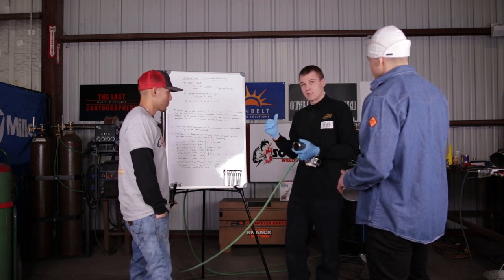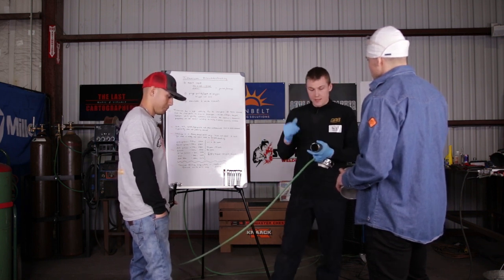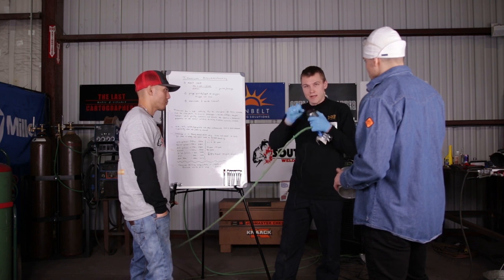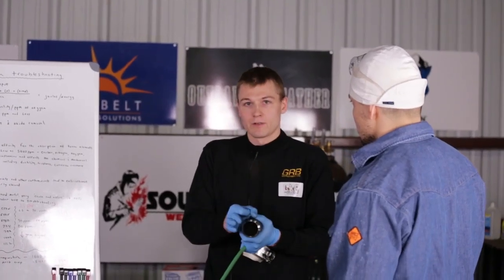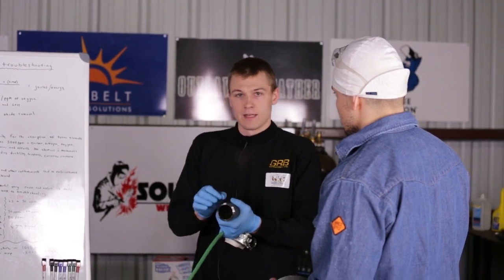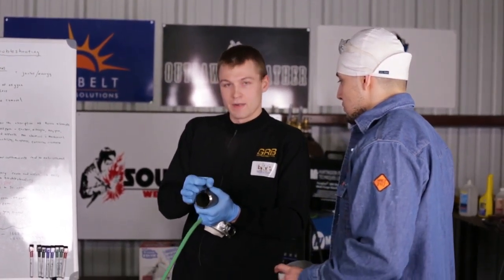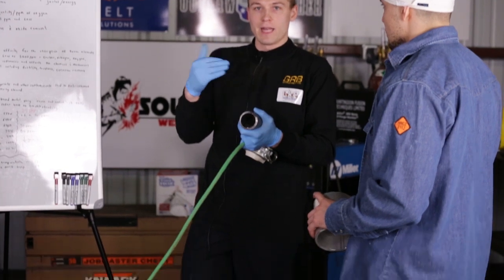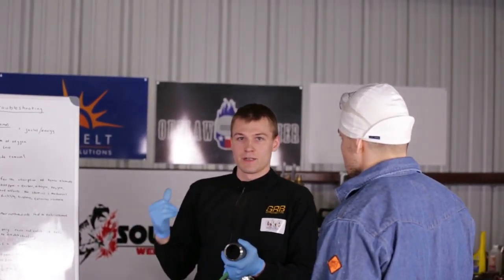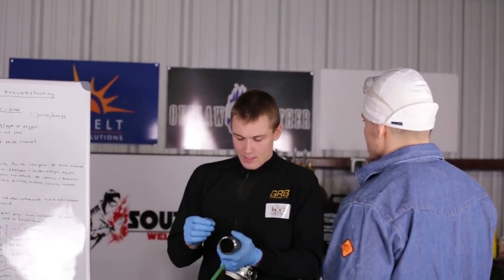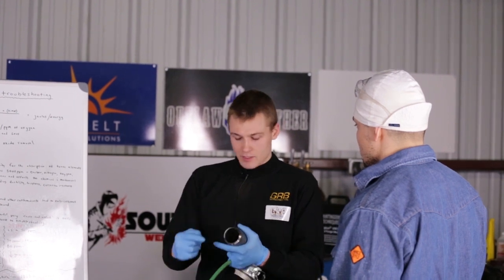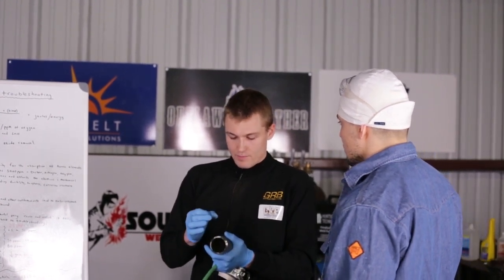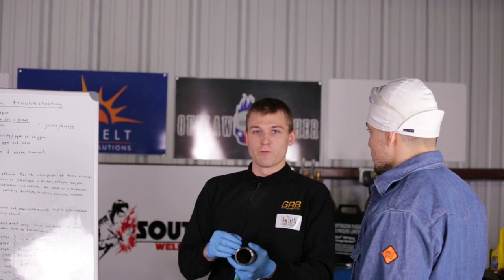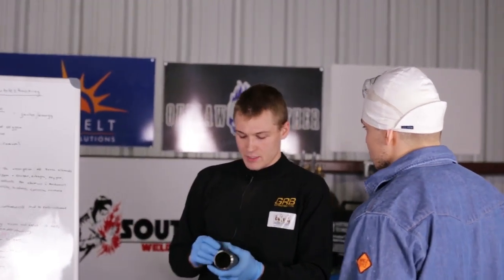Whereas if I have the machine set to 350 amps and I give the surge of current, my input is going to be instant, it's going to wash that ripple out instantly, and I can drop the current to keep the higher frequency on. Once it creates a ripple, I can drop it down, and because it's expelled less energy than it would have if I had the machine at 200 amps, it depends on how much energy you expel into the material how long you need to protect each individual ripple, depending on the amount of energy you expel into it.